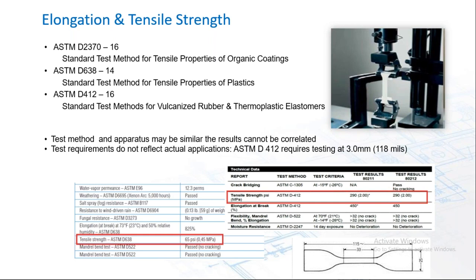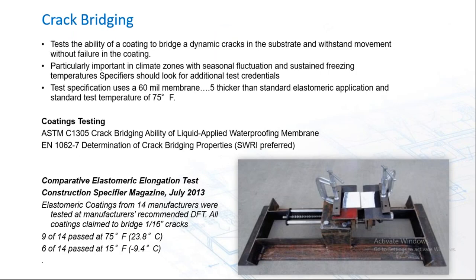So crack bridging is another interesting one here, and this is obviously an important test from the point of view of concrete. We know it is going to crack sooner or later, and it tests the ability of a coating to bridge dynamic cracks and withstand movement without failure of the coating.